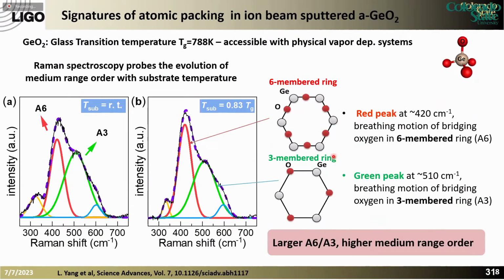So we have been studying the medium range ordering in amorphous oxides deposited by sputtering. And we chose, in this case, a material, germanium oxide, that actually has a glass transition temperature of 788 degrees Kelvin, which is accessible with a physical vapor deposition system. And so using Raman spectroscopy, we looked at the organization defined as the population of 6-member rings and the population of 3-member rings.